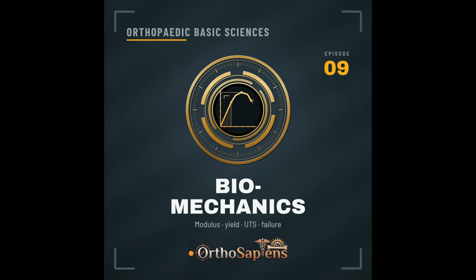Exactly. When you hammer a metal implant down into a femur, the metal stem and the surrounding bone now have to share the load of the patient's body weight. If you use an incredibly stiff implant, like a massive cobalt chrome stem, that stiff metal is so unyielding that it ends up carrying almost all of the body weight itself. The adjacent bone is shielded from the mechanical stress. Stress shielding. The bone is essentially sitting there, completely unloaded, thinking it has been retired. And because it is unloaded, Wolff's law dictates that the bone resorbs. It thins out. Over time, as the bone melts away, the implant loses its tight fit, it loosens, and the entire joint replacement fails. This is why titanium is so incredibly valuable.